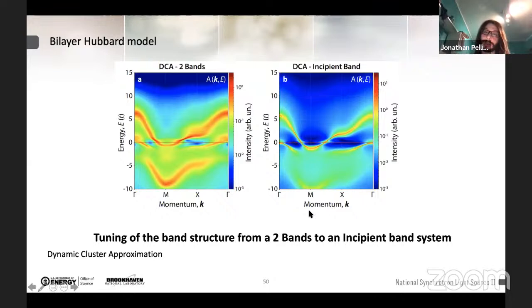where they could tune the spectral function that I'm showing here as a color plot from a two-band system presented here on the left, which has a hole pocket close to the gamma point and an electron pocket at the zone boundary. And by changing the parameters, they could tune this model into what is called an incipient band situation, where the hole pocket at the gamma point is shifted below the Fermi level and only the electron pocket at the M point is left. After these initial calculations, they could extract the spin susceptibility, which is what I'm presenting here.